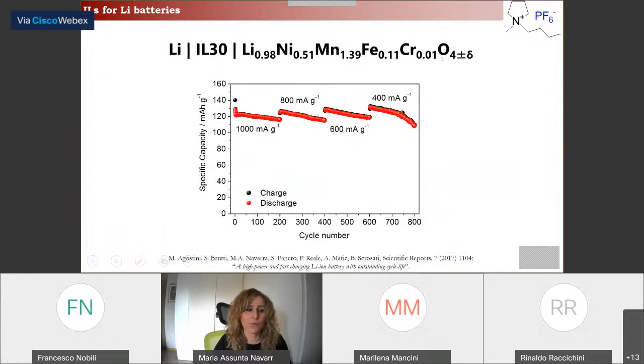Better performance was obtained when the mixed electrolyte with 30% ionic liquid was used in combination with a homemade spinel cathode containing chromium and iron dopant. In this case, indeed, a very long cyclability and good stability was obtained at particularly high current density rates, up to 10 C.